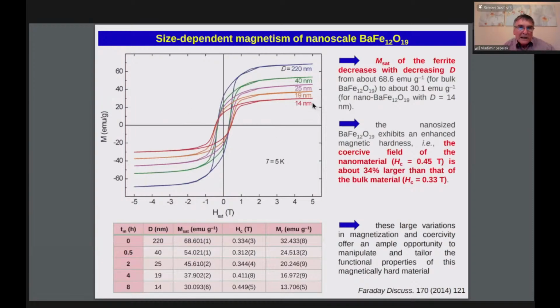And here is just a comparison of the magnetization of the mechanosynthesized material. This is the red hysteresis loop for nanoparticles with a size of about 40 nanometers. You see that we have a relatively small value of saturation magnetization, which can be adjusted by thermal treatment, and we can obtain particle sizes up to 220 nanometers, as demonstrated here.